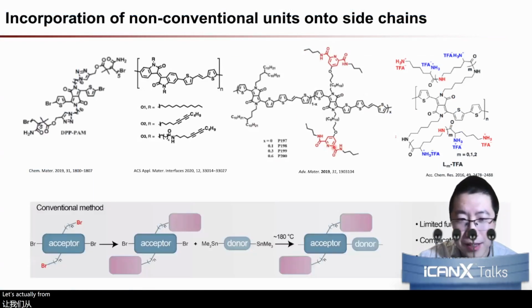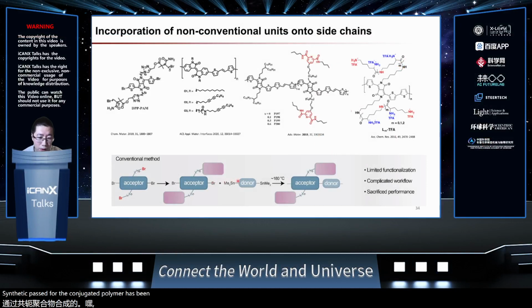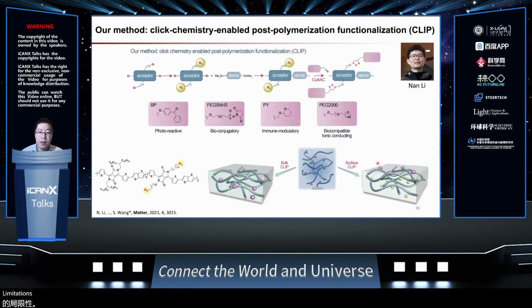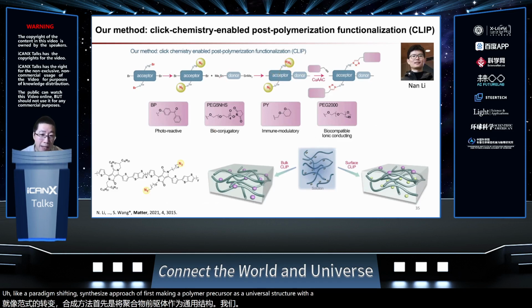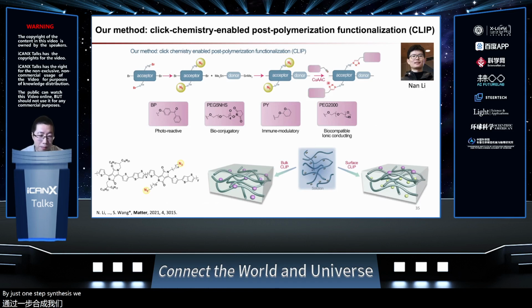But actually, from the synthetic point of view, this is quite challenging because all the existing synthetic paths for the conjugated polymer have followed synthesizing the monomer with the target structure first, and then polymerizing at the end as the last step. Therefore, it causes significant limitations. So more recently, we have designed a paradigm-shifting synthesis approach of first making a polymer precursor as a universal structure with a reactive group at the end. Then using this universal polymer design, we can put on almost any type of chemical structure or functional unit by just one step of synthesis, very simple, onto the side chain. So this can be carried out both in solution for realizing bulk modification throughout the entire film after spin coating, or on the spin coated film only as a surface modification.